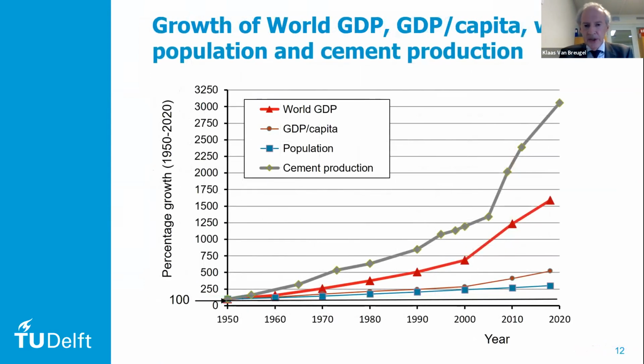Interestingly, this picture shows that cement has played an enormous, important role in this. If you look at the red curve, which shows the increase in the gross domestic product worldwide, on the time scale from 1950 to 2020, so the last 70 years, then you see that there is also an enormous growth in the amount of cement, with this gray curve, and the growth in the consumption of cement is even higher than the growth in the gross domestic product.